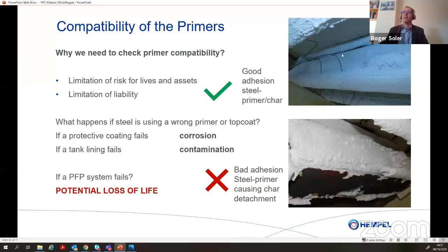This is simulating a three-sided beam. Here you can see the web and the flanges, and those lines here are the thermocouples that we install to check the temperature during the experiment. And on the top, it worked. So the char developed. It produced this white char that is doing these insulation properties, while on the bottom, there is a primer that looked okay in the cold state, as we call it. So there is a good adhesion in normal conditions for a paint. But when it comes to fire, then the whole system just falls out.